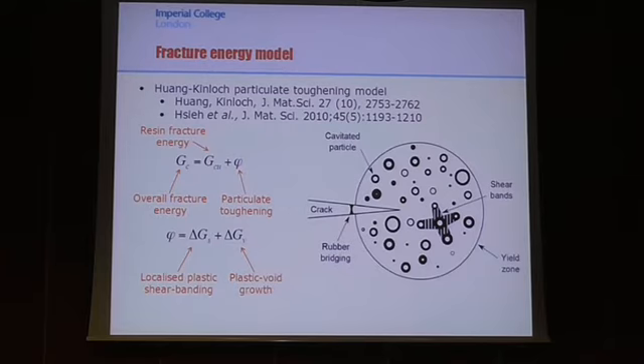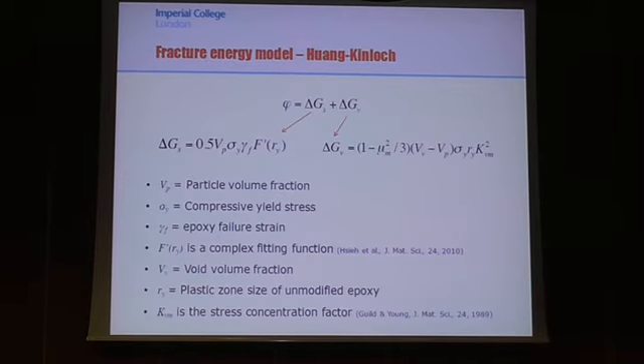So we used the Huang-Kinloch model, which was from about 1992, which says that the overall fracture energy is the sum of the resin fracture energy plus the toughening mechanisms from the particles, which can be identified as localized plastic shear banding and also plastic void growth. These are the equations that were worked out by Huang-Kinloch back in '92. All of these can be measured. Particle volume fraction can be measured. Compressive yield stress was measured earlier. Tensile failure strain was measured.